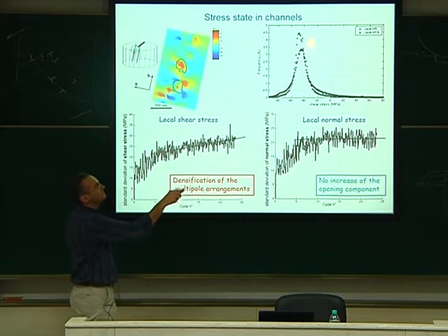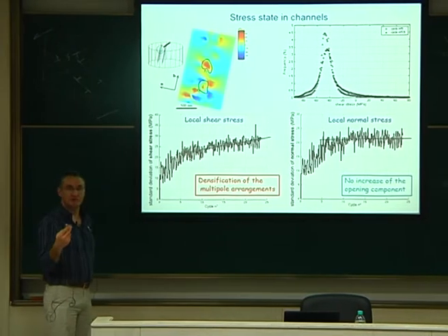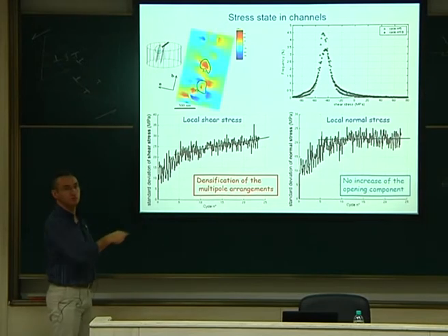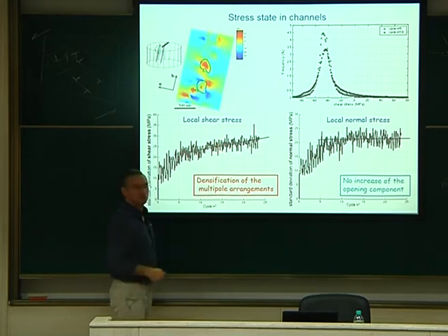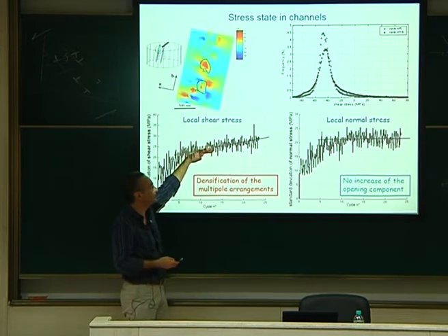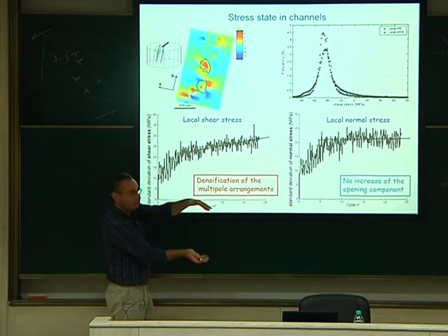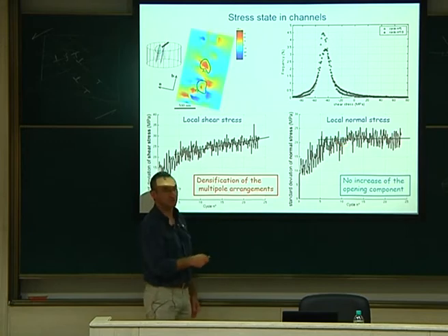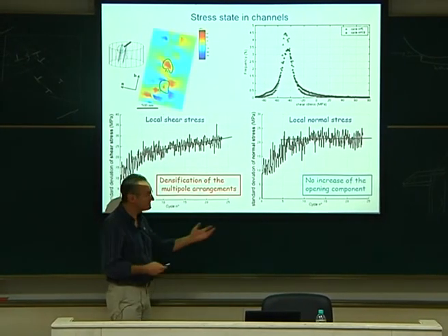I can make the same statistics about the tensor, but then I will derive two quantities, either the shear or the normal stress. The shear stress, localized here, is always increasing. So this is just because you have more and more dense dipoles. The dipoles are denser and denser, so the shear stress, which is the cumulative shear stress of the dipoles, is always increasing. If you look now at the opening component, the one that would open the crack, it is not increasing, it is saturating. So the answer is no, for my simulation at least.